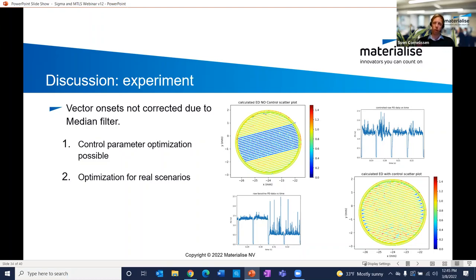So it takes our control loop a bit of time to drive the laser power up, to drive the energy density back to the nominal value. So that is a consequence of that median filter that we have on the incoming raw data. Besides that, what you can see is that the control loop drives the energy density to the nominal value in a very straight line. You can see that best in the raw data, meaning we've made the control loop quite aggressive, I would say, to control out these defects that we artificially induced.